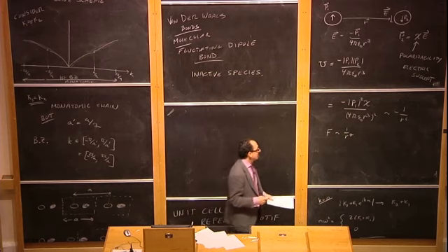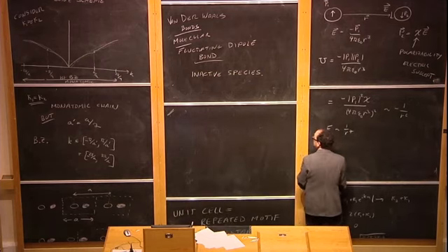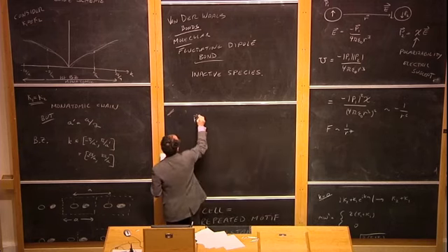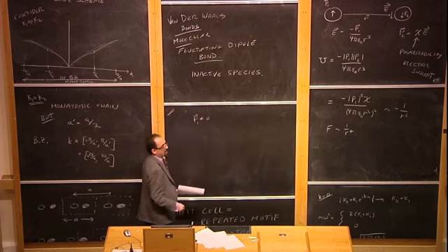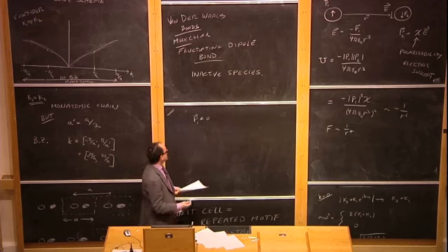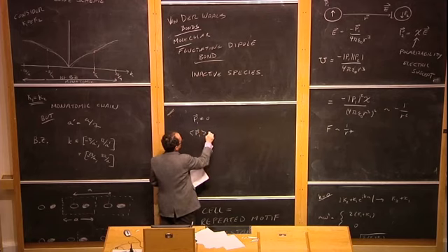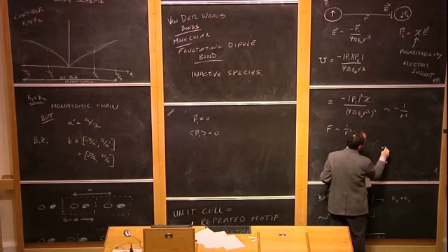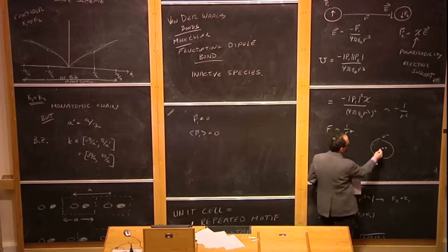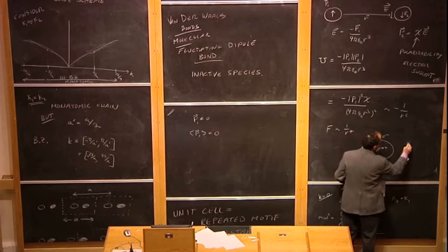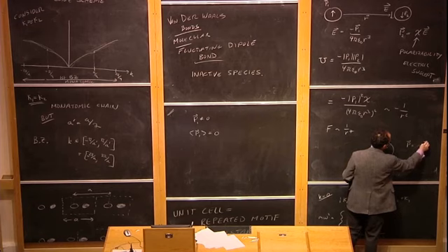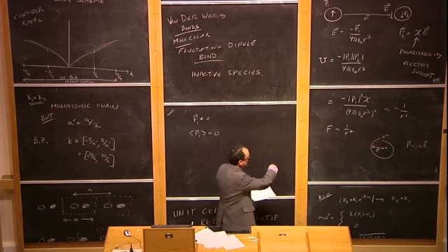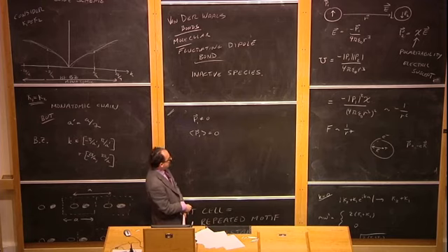But you might say, well, wait a second. This whole argument was predicated on the statement that the polarization is not equal to 0 to begin with. But in a spherically symmetric atom like helium, the expectation of the polarization is 0. Why is that? Well, you remember that the polarization of an atom, here's the nucleus, here's the electron. The electron's running around the atom in some sort of spherical orbit. So the position, r, of the electron is related to the polarization just by minus e times r or something like that. So we're just saying that the average position of the electron is actually at 0.